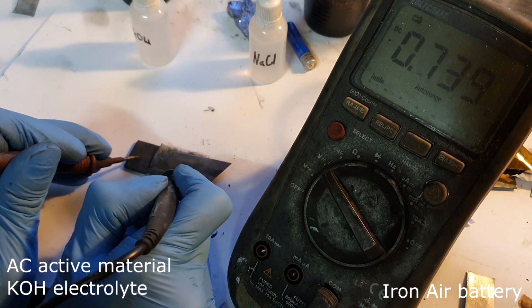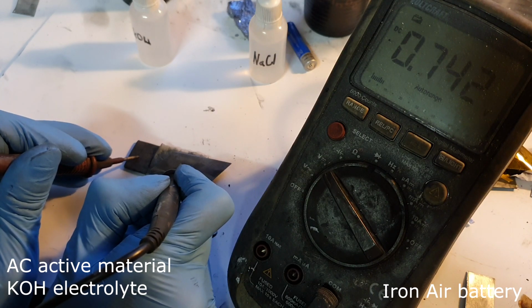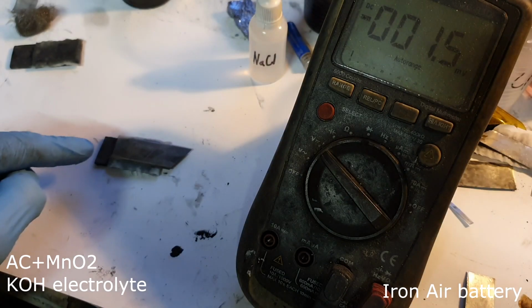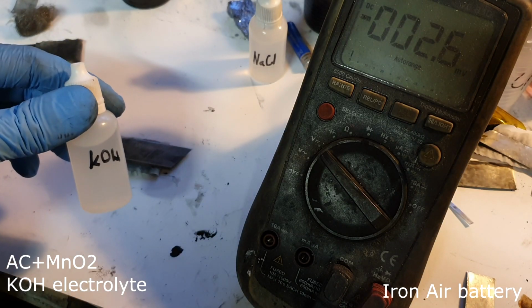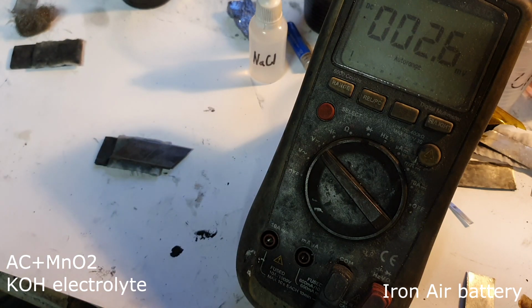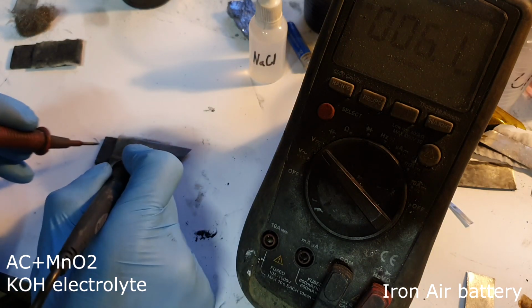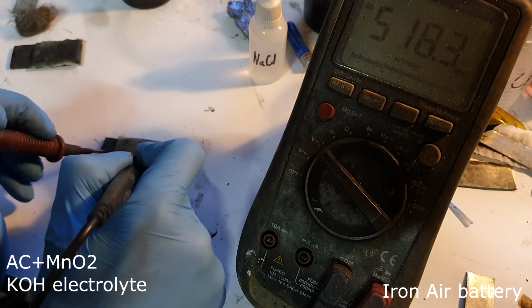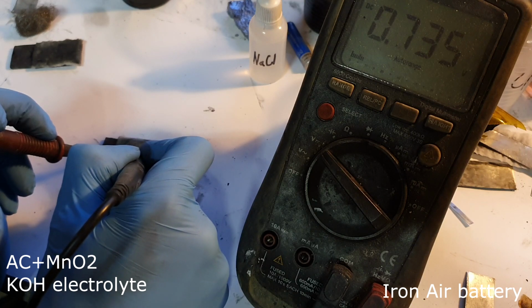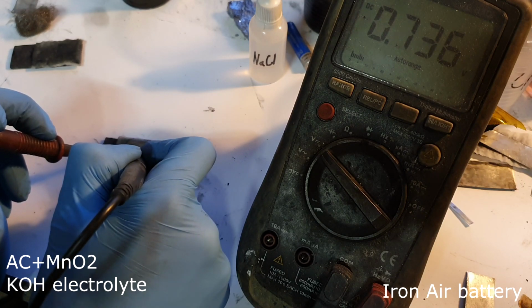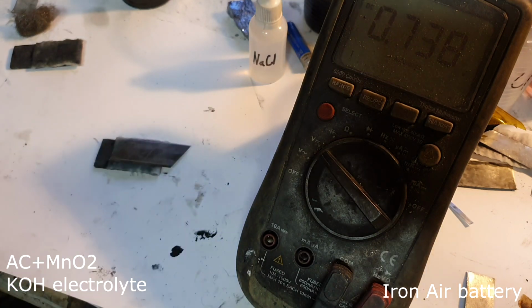And the voltage here is 0.74 volts. So this iron air battery has the electrolyte which is potassium hydroxide, but together with activated carbon has some small amount of manganese dioxide. And let's see if we get a little bit better voltage. And yeah, the voltage is still 0.73 volts.